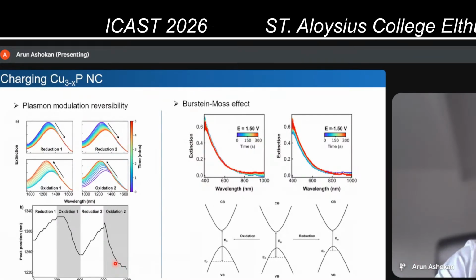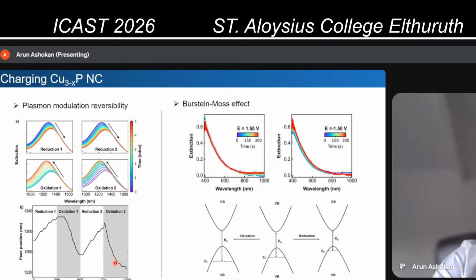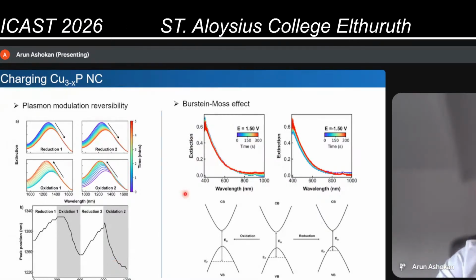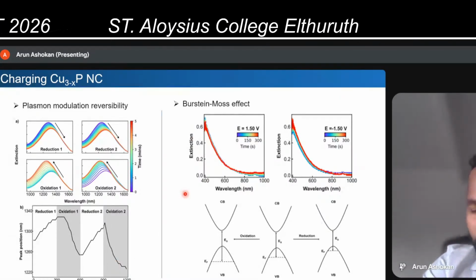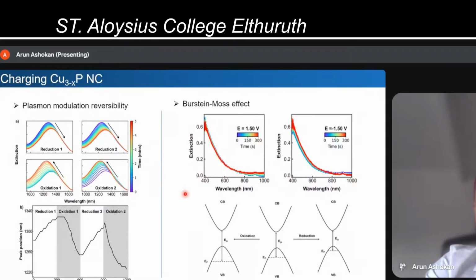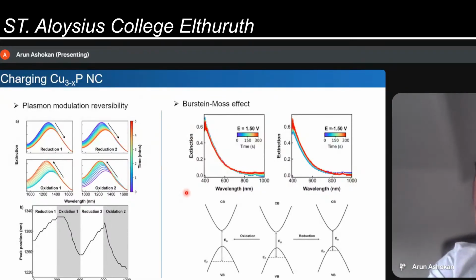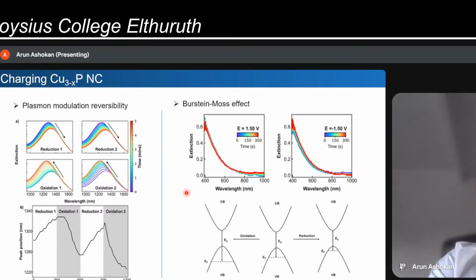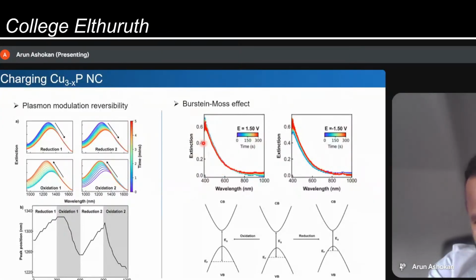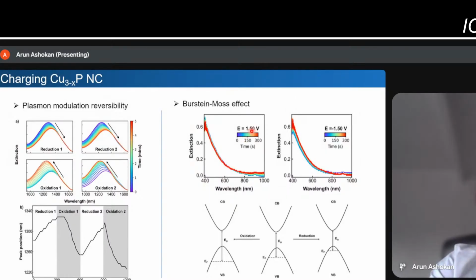Other than this, as I said, this is a semiconductor. So this material has some band gap. We can also see the changes in the band gap when we charge these materials. If you look at the absorption spectrum, when you oxidize the nanocrystals by applying a positive potential, you can see that the absorption spectrum is blue shifting.